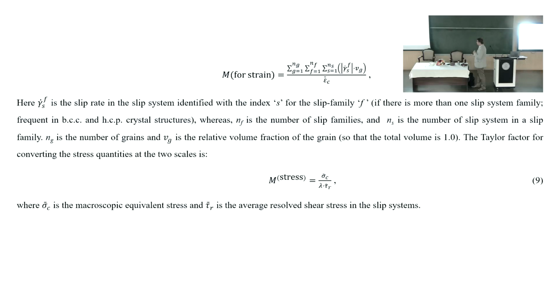For the stress transformation, we will have the macroscopic stress here, and this is the microscopic shear strength of the material, tau r, average, here. So one would think that it is just the ratio here, like for the strain. But no, not really. This one we know here, in the simulation, and by averaging, we also know this one. So we can get the Taylor factor to transform our quantities into macroscopic ones.